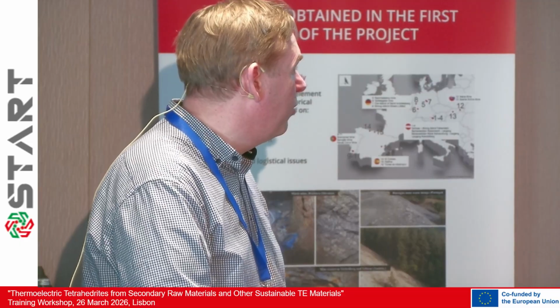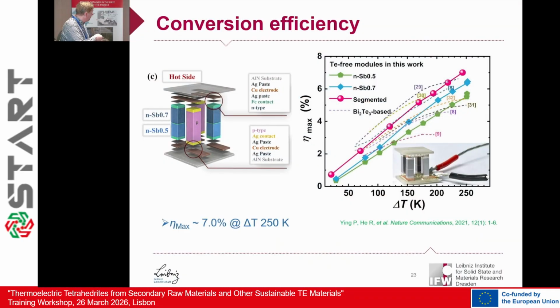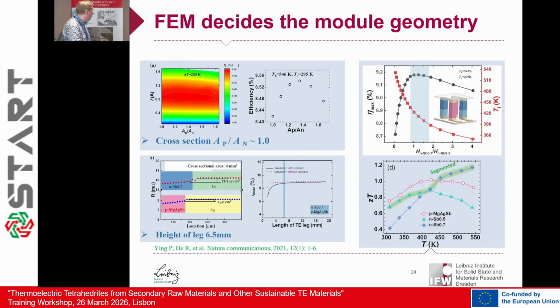I think the most recently optimized N-type material even reaches a ZT of 1.4 or so. So I think it has very promising results. These were the earliest data. We had an efficiency of about 7% when we did this combination, segmentation of the N-type and P-type material as a whole. And we applied a temperature gradient of 250 Kelvin. And I think this is already roughly 5 years ago.